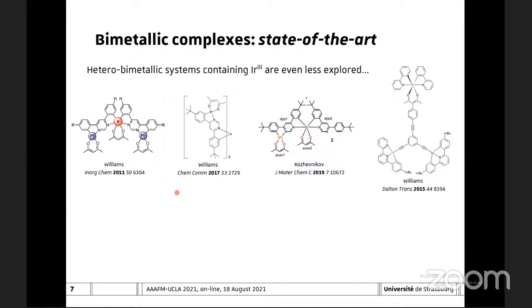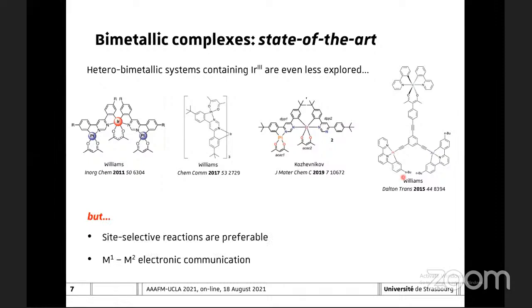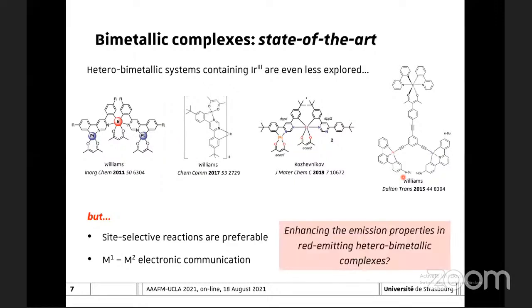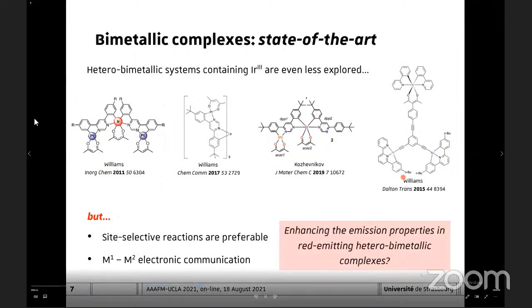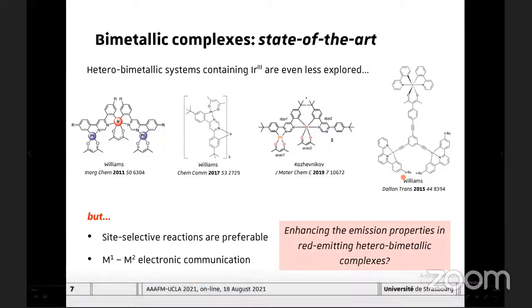with only the few examples known in the literature that I show here in the slide. This is because they require site-selective reactions in order to improve the reaction yield, and also careful design of the ligand environment and the metal, in order to avoid metal-metal electronic communication. So we were then wondering whether it's possible to enhance the emission properties in red-emitting heterobimetallic complexes.